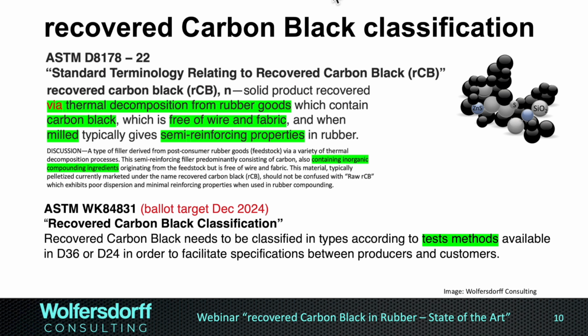We have an interesting work item, the ASTM work item 84831, which is for ballot in December 2024, which is the recovered carbon black classification. So it's a similar classification as we have for furnace carbon blacks. And the most important thing, ASTM says we only accept ASTM methods for that classification. And these methods can be either from the committee D36, recovered carbon black, or D24, which is the furnace carbon black committee, or the D11 committee, which is the general rubber committee.